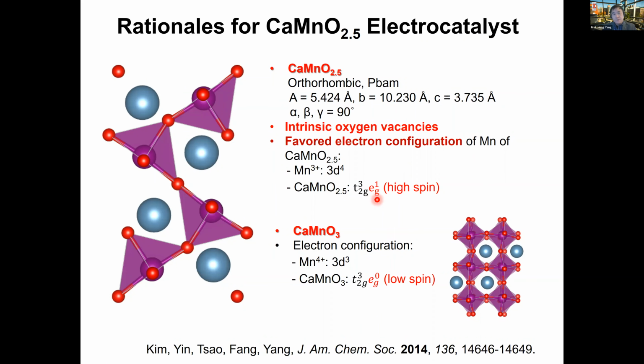So that turns out to be a feature that electronically favors the OER performance, as proposed and illustrated in the Science paper I mentioned earlier. So this turns out to be a win-win situation. Not only will it open up the oxygen lattices, but it also changes the electronic state.